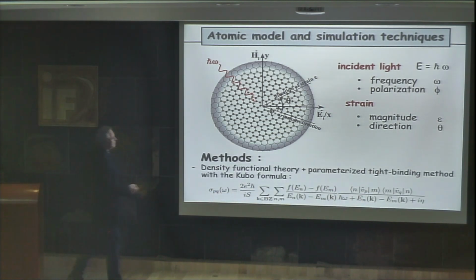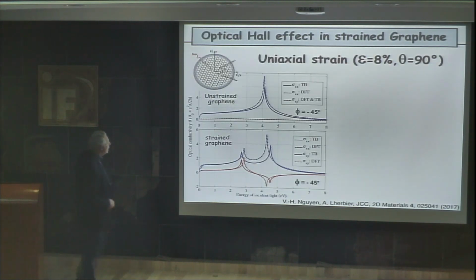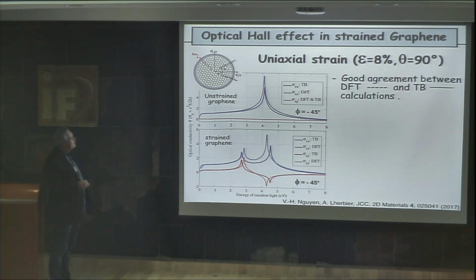And we use also, again, density functional theory and also tight binding methods to calculate the optical conductivity and the optical Hall conductivity in the system. And so if we do that, first without the presence of strain, you remember the curve that we had in the case of Borophene, we still conserve that same curve for graphene here, for the optical conductivity without strain. And you see that the optical Hall conductivity is, of course, 0 because we do not impose any strain, so there is no lattice symmetry breaking in the system. You see that we have a very good agreement between DFT calculation and the tight binding model, so the linear curve and the dash curve in this study.